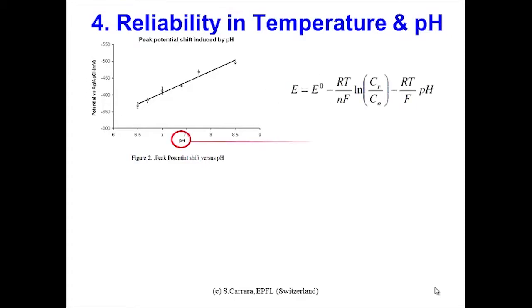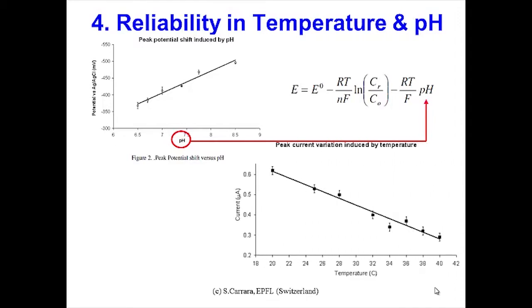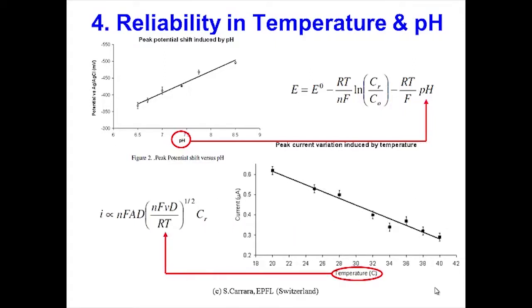The reason is, of course, that the Nernst equation has an explicit dependence on the pH, so we cannot cope with that. We can only measure the pH, mark the variation, and calibrate our sensor. The same is true for the temperature. Both the Randles-Sevcik equation and the Cottrell equation have an explicit dependence on the temperature. So once again, if our patients move from 36 up to 40 degrees, we have a significant variation of the current we measure. The current is typically directly proportional to the concentration of our metabolites, and so we mix up the real concentration. So we definitely need to measure pH and temperature.